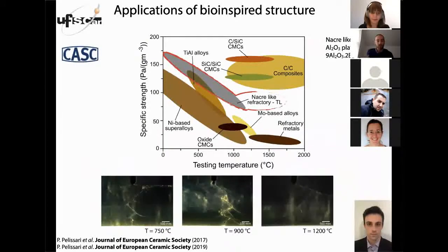So Pedro was very interested in high temperature materials, so we also tested these composites at up to 1200 degrees. And you can see here the value we have, plotted in the map of all the different thermostructural composites we are using today. You can see, for instance, the nickel-based superalloys that are used for plane engines, or the new generation of materials for plane engines, the carbon-carbon composites. And you can see that in specific strength, we're better at these different temperatures.